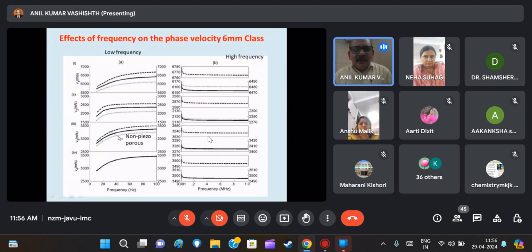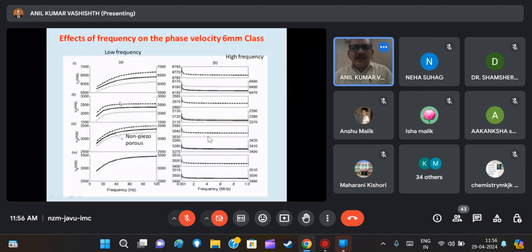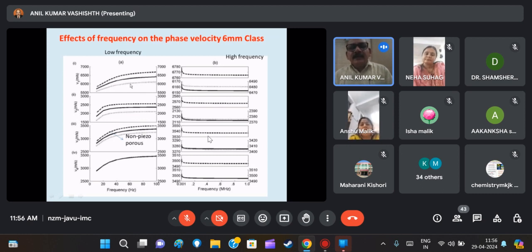This is for the low frequency, and you can see this solid curve is for the case when non-piezo porous material is there. That means when we neglect the piezoelectric effect from the porous material, this curve will be obtained, and these velocity curves match with the existing velocities of porous materials when the piezoelectric effect was not there. So for the validation of our results, these solid curves are shown, and they match with the existing literature.